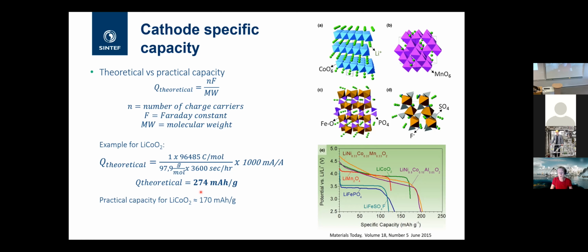milliamp hours per gram. But in practice, you get about 170, which is also shown in the figure here. That's the green line. The reason for that is that the structure for the lithium cobalt oxide is shown up here in A, where the green dots are the lithium ions. And these polyhedra are, in this case, the cobalt oxide octahedra. If you have nickel or manganese in there as well, you would have nickel or manganese occupying the middle of the octahedra. So the NMC, the lithium cobalt oxide, and also another material termed NCA, they all have the same basic structure, which is this layered structure right here.